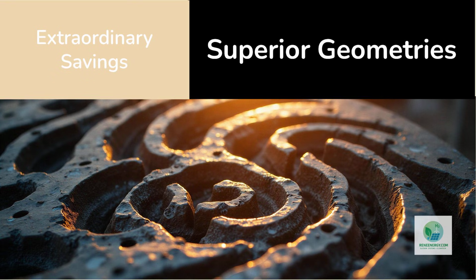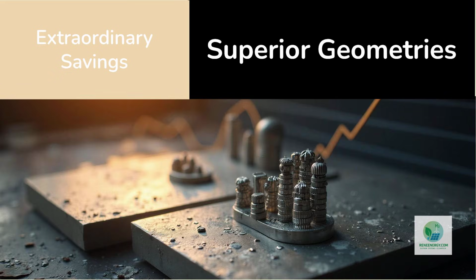The geometries achievable using Exentis' method are far superior to machined parts. Curved channels, fractal flow patterns, micro-lattice reinforcements, and internal structures that were previously impossible now become standard. More efficient flow channels reduce pressure drop, improve gas removal, and increase stack efficiency. In one breakthrough, the company printed plates weighing significantly less than their machined counterparts while outperforming them in fluid distribution. When one component of the electrolyzer drops in cost by 10x and improves performance, the entire cost curve shifts. This is the first pillar of proof.